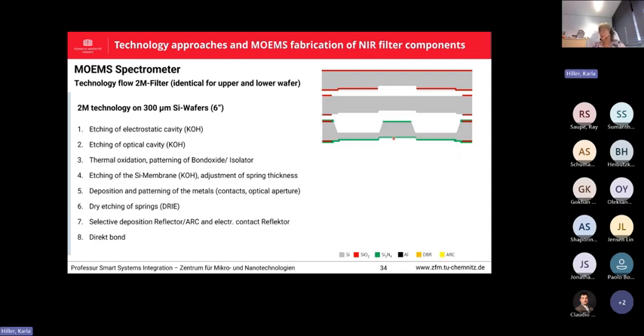Everything is protected by silicon nitride, and again we do the etching of the membranes. And then the nitride is removed, aluminum is deposited first and patterned, and finally in this case we use the dry etching of the silicon with the Bosch process to get the movable structures and the springs.